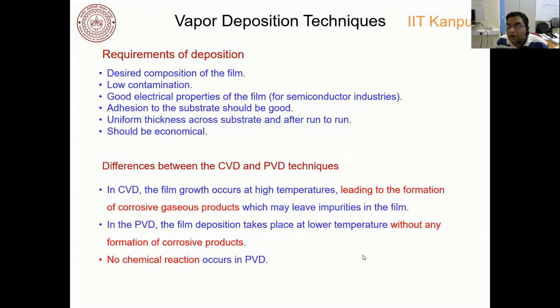And when you talk about the differences between chemical vapor deposition and physical vapor deposition, as I said, vapor deposition is of two types, chemical vapor deposition and physical vapor deposition. You will see that in CVD, the film forms at high temperature, leading to a formation of corrosive gaseous products, which may leave impurities in the thin film that you are depositing, right? So you have to make sure that these products that are formed are pumped out of the chamber efficiently. Otherwise, they will form contamination.